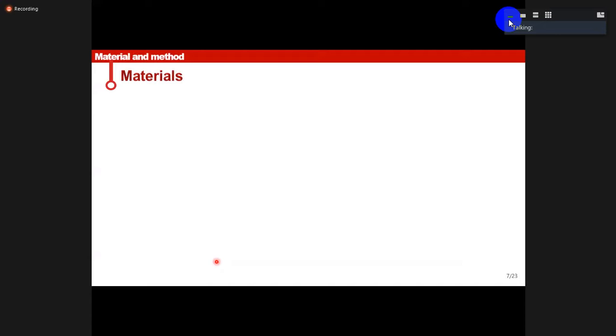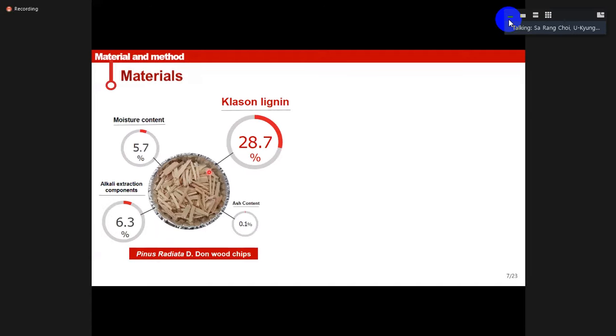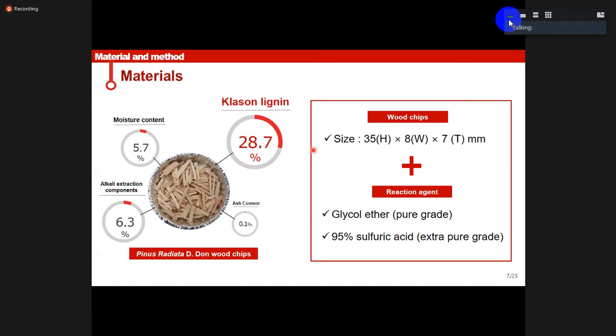In this study, we tried to produce fibrillated fibers through an alkali kneading treatment. In addition, the effect of pulp concentration and kneading time on fibrillation properties was analyzed. Radiata wood chips with lignin content of 28.7% were used as raw materials. Matchstick-size chips were used for organosolv pulping. Also, glycol ether and sulfuric acid were used as reaction agents.